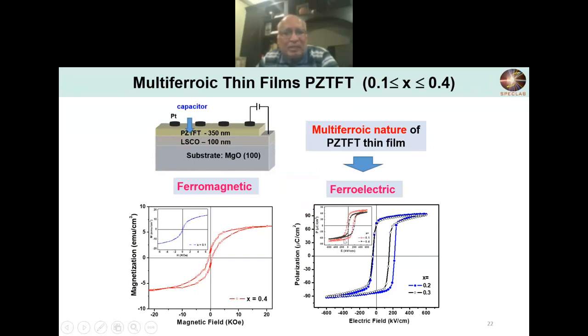Here are the polarization measurements. Actually, you can see excellent ferroelectric loops for x equal to 0.2 and 0.3, which, as I said earlier, were actually the most reasonable values of the polarization and magnetization. And here you can see very nice ferroelectric loops. And here are the magnetic loops of this material for different concentrations.